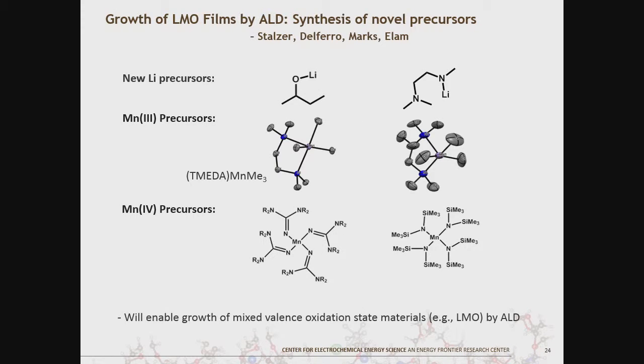We've yet to confirm that if it has the right oxidation state and structure and so forth, but that work is ongoing. Tobin Marks' group and Madeline Stalzer at Northwestern are actually working to design new precursors. Manganese is a really big challenge. If you want to grow LMO, you'd like to grow it in a mixed oxidation state in principle, so you'd like to have manganese 3 and manganese 4 precursors. As I understand it, there's very few precursors available for manganese, so they've come up with these various types of molecules, and we're testing this now to see how well we can grow materials by ALD.